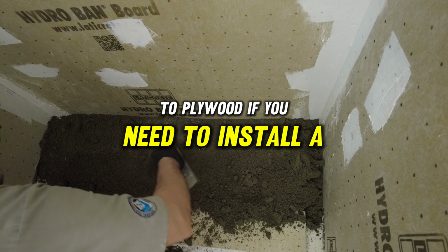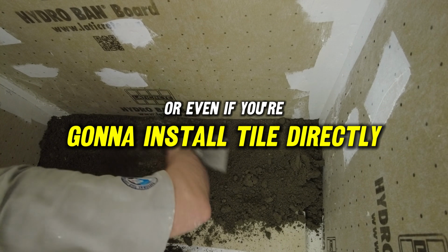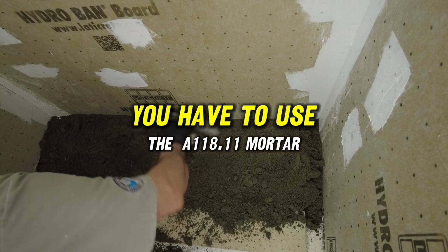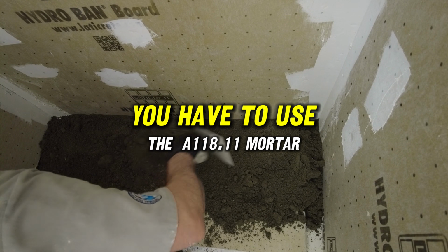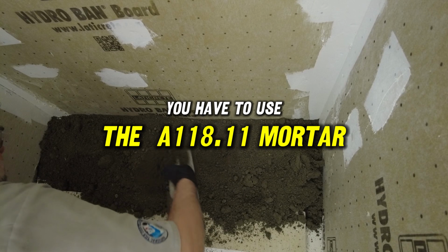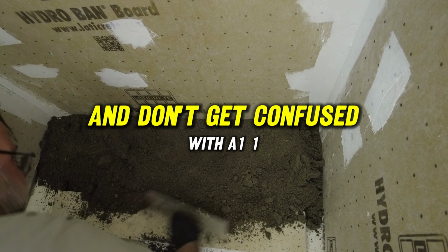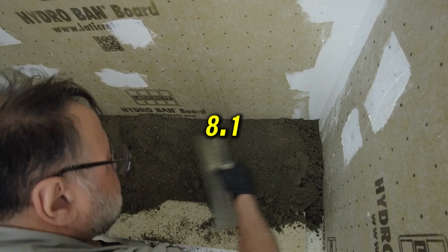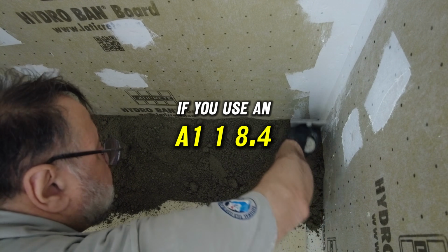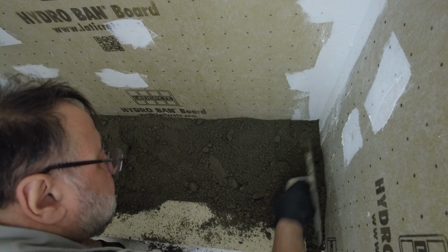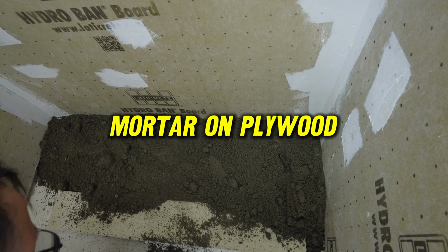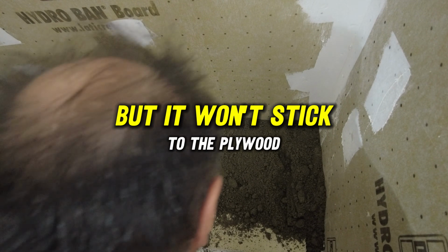If you need to install a membrane, or even if you're going to install tile directly to plywood, you have to use the A118.11 mortar. And don't get confused with A118.1, which is unmodified. If you use an A118.4 mortar on plywood, it'll stick to the tile, but it won't stick to the plywood.